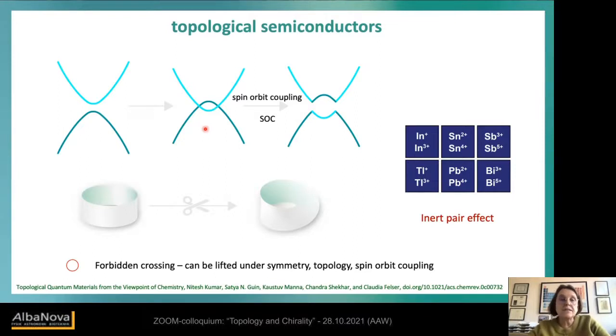So, and very common is this really in heavy elements, also for another reason, not only for the size of the atoms, because also if we go to heavier elements in the periodic table, the 1s electron becomes faster, nearly the speed of light. This leads to contraction of the outer s electrons, and very often this is the 6s or 5s electrons or even 4s electron of an element like indium, tin, or lead, which then goes lower in energy, so it overlaps, as a conduction band, it overlaps with the valence band, and then we get these crossing points here. And depending on the symmetry, these crossing points become forbidden crossings, and especially if we have heavy elements, spin is not a good quantum number, so this is very often a forbidden crossing, so it allows that this crossing is forbidden, so we open up a band gap and we get the situation like we see here.